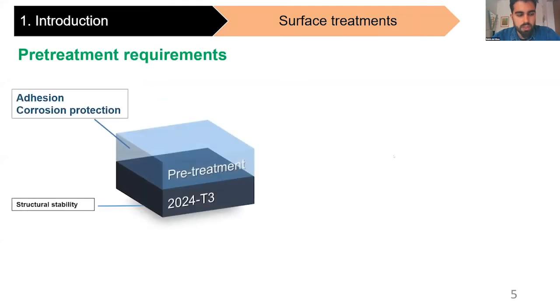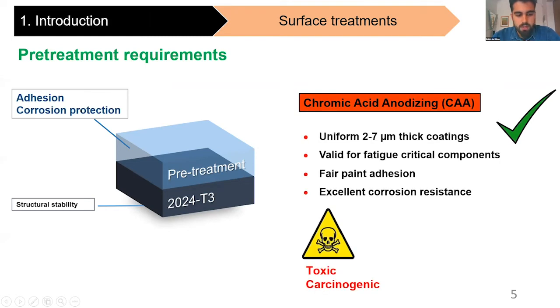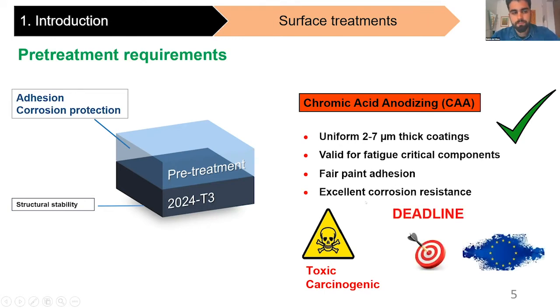It should be noted that the quality of this multi-layer protection scheme depends on the quality of the pretreatment, which must show high adhesion and corrosion protection. So far, the most widely used surface treatment is chromic acid anodizing, which promotes the formation of uniform coatings with thickness between 2 and 7 microns. It's valid for fatigue critical components, offers fair paint adhesion and excellent corrosion resistance. However, the use of chromium-based compounds has been targeted as toxic and carcinogenic. For this reason, the European Union required its elimination before 2024.